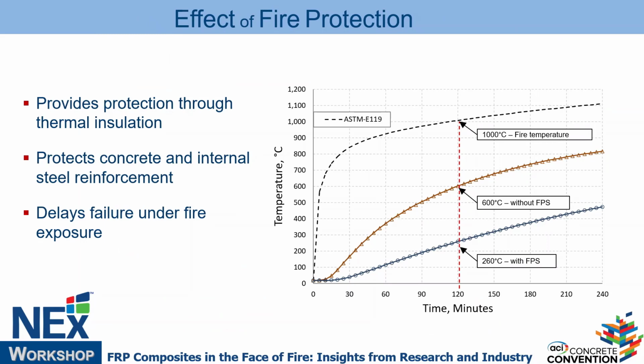So here, for example, is a test. This comes from a UL test. The temperature of the steel bar with and without fire protection. So this is without the fire protection system, 600 C. This is a curve in the middle, right? While the lower one drops to less than half the temperature, 260 C, right? And that's what matters, because if I get this temperature low enough, sometimes I can even maintain the full yield strength after 2 hours and 3 hours.